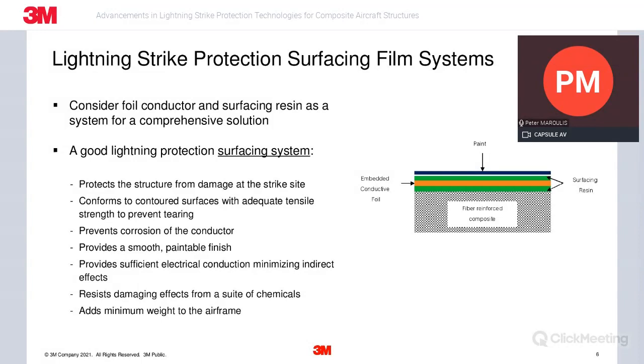There are a lot of functions that this outer layer must perform. These are listed in the slide here. It protects the structure from damage due to lightning strike. It needs to provide a smooth paintable surface, hopefully with little to no paint holes. And there are a bunch of secondary performance requirements that make it a good system. It needs to prevent micro cracks from forming that could allow moisture to get in, which could cause corrosion in the embedded foils. There's also a need to remove the paint and surface for various reasons. So these systems should require adequate performance against the chemicals used for cleaning and paint stripping.